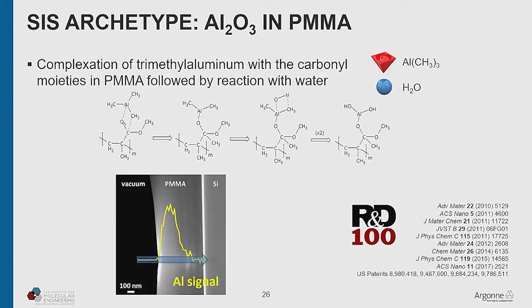And just to show you that you can in fact grow bulk material here, this is a cross section of a thick PMMA film. So I'm a nanoscientist, 500 nanometers is thick. And this is an elemental signal of aluminum going into that film so that you can see that aluminum oxide has been grown 200 or 300 nanometers into that film. And again, it's diffusion limited, so you can play with the depth at which you grow the material by changing temperature or pressure or other things that are obvious knobs for diffusion.